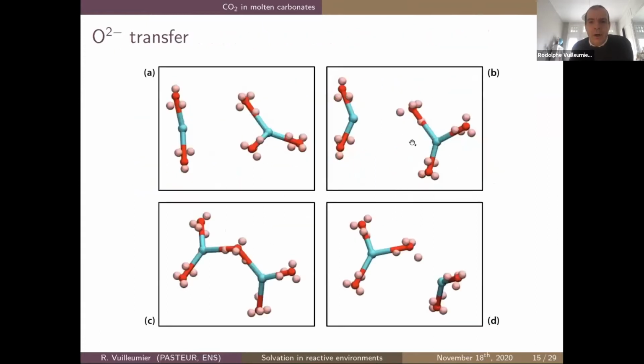We could check that these are indeed hops of O2-. Here I put in pink the Wannier orbitals that represent the doublets, the electron pairs in the system. You have 4 of them around each oxygen, and when the oxygen transfers, it actually transfers with these 4 doublets, so 8 electrons. So indeed, this is an O2- that transfers, and there is no independent transfer of Wannier orbitals. They actually move along with the oxygen, stick to the oxygen, so it's really an O2- transfer.